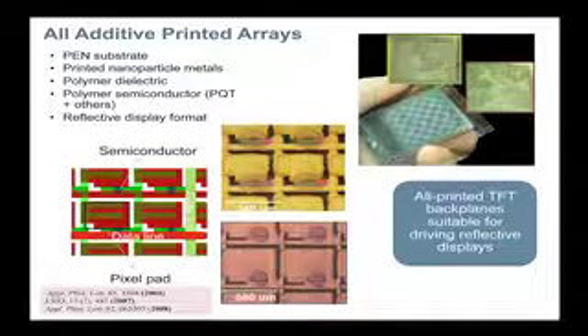So when you get everything to work, we were able to demonstrate fully printed TFT backplanes, where our process was only 4 layers. There was one layer to deposit the gate layer. The gate layer in the TFT backplane is really turning the pixels on and off, which is this green layer. The red layer is the data level where you send the information that you want to write in the display. And the blue dots are the printed semiconductor.